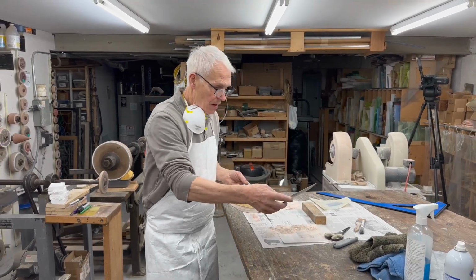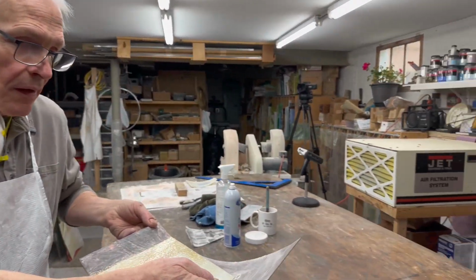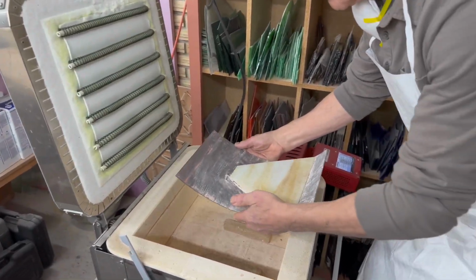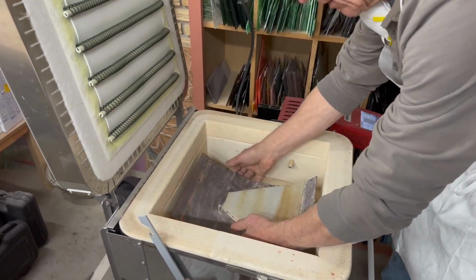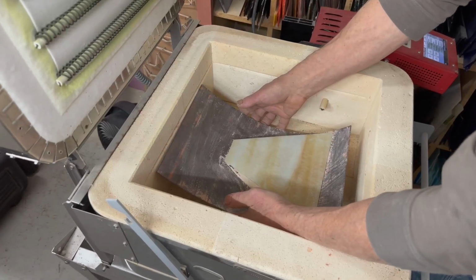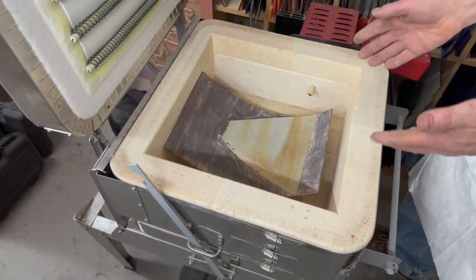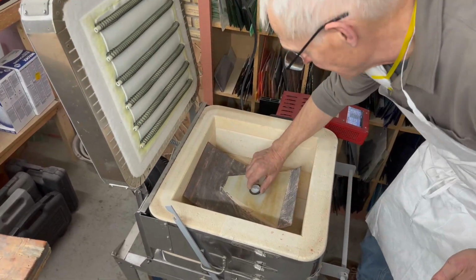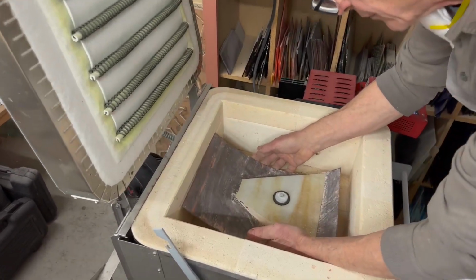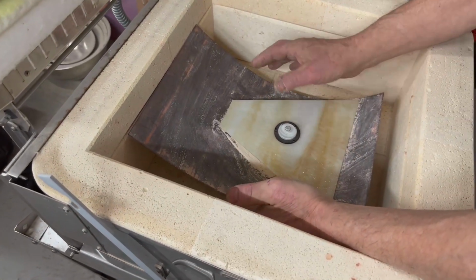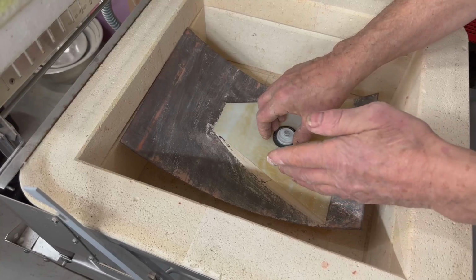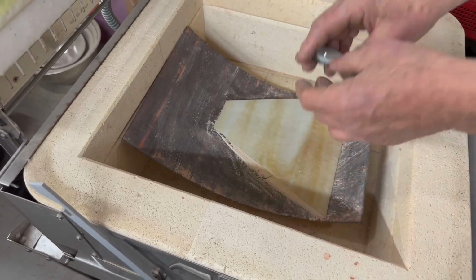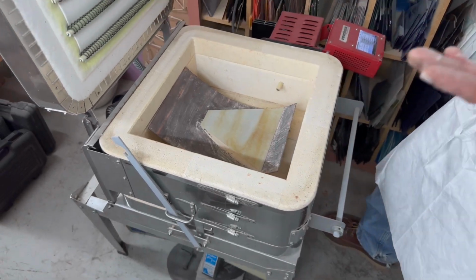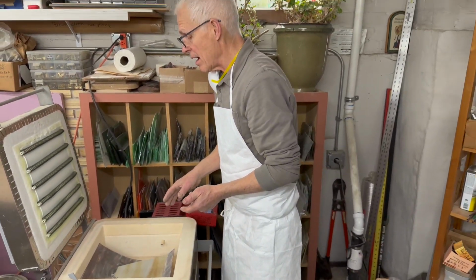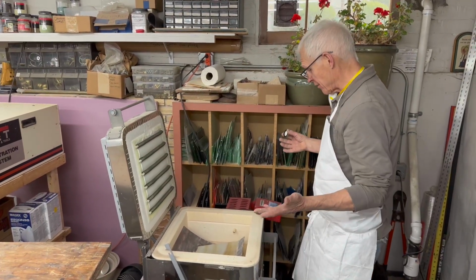Sometimes it's easier to put the glass in, or rather on the mold in the kiln rather than prior. If you want, you could possibly take a level and try to get it close to level, so that when it falls and slumps down into the powder, the powder will support the glass just fine, and it'll fall almost perfectly.